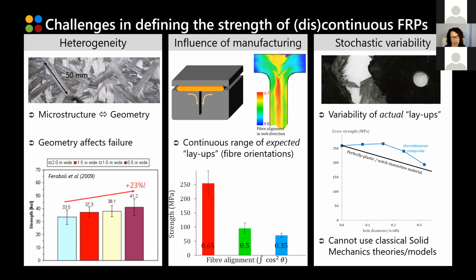So the fact that we have a microstructure which is heterogeneous at such a large scale means that the geometry of the specimen that we are testing definitely affects the failure process. You can see here in the plot below that if we test specimens with different widths, by changing the width by a factor of 4, you can easily increase the strength of the composite that you are measuring by almost a quarter, which is something that we have also seen in Michael's presentation happens for continuous composites, but it is a much stronger effect that we see in this type of